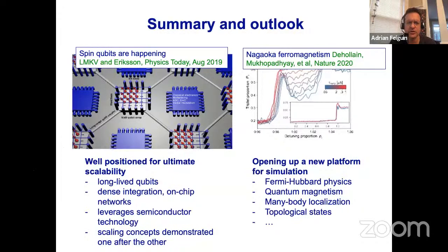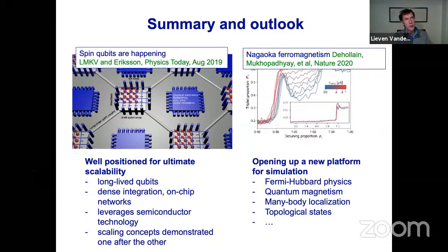Is it possible to tune the parameters in your quantum dots such that the interlevel spacing inside the dot due to confinement is of the order of the Coulomb repulsion between electrons? So we would tune it not by the gate voltages, but more by the design. The dependence on the size is different for the orbital quantization energy and for the charging energy, and that's where in principle, yes, you could reach that regime.